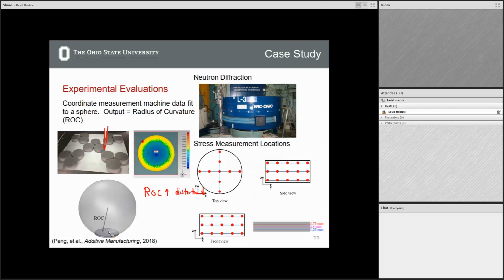All right, the other thing that we did is we took these samples, and the postdoc ran up to Canada, like the middle of nowhere Canada, where they have this neutron diffraction instrument, and he was characterizing the stress at different locations in this part. So this is trying to get similar data that Brian presented, the crack compliance method, which has some problems with it. One of the problems that he didn't mention is that it's destructive. Right? So this is a non-destructive way to try and get the stress in the part. And so this is nice in that way. The main negative is that you have to send a student to Canada or Oak Ridge or Argonne. There are not too many of these things. They're not just lying around.